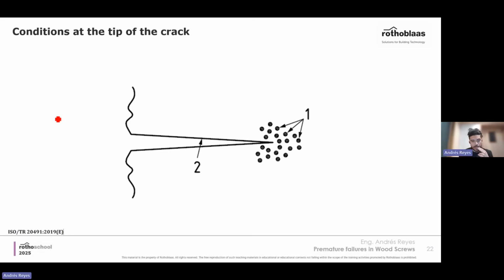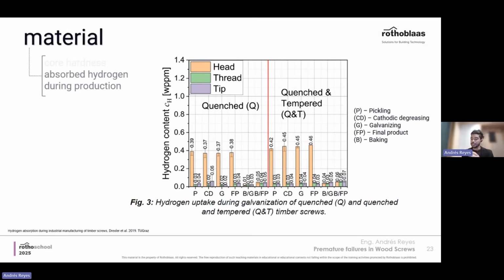It's important to say as well that once a crack is in place because of any factor, because of incorrect installation, because of a bending of the screw that comes from incorrect installation, or some unexpected loads, the presence of hydrogen would then assist the formation of the crack. So, independently of the source of the crack, hydrogen in this case would be the number one. The hydrogen will then assist the completion or the advancement of the crack as well. And that's hydrogen embrittlement. So let's go back to the sources of hydrogen.